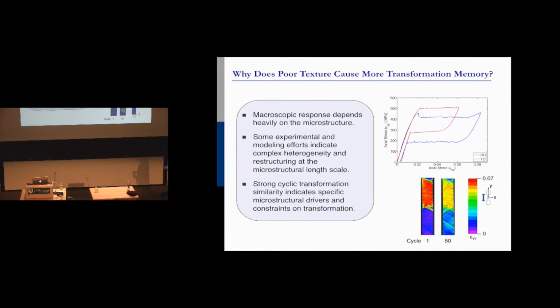There was some experiment that had just come out that indicated that this idea that Miyazaki had, that you have one variant that subsumes the entire grain, wasn't right. There were some qualitative experiments that had come out with filtered microscopy that seemed to show that there were areas of the grain that were transforming more than others. So that was just starting to come out. And then we found this really strong cyclic transformation memory for the first time, that kind of showed that there had to be some sort of really specific microstructural constraints on transformation. There was something that was driving it to transform the same way over and over.